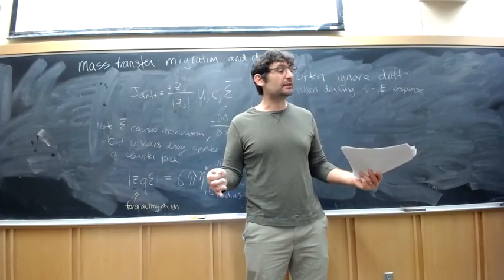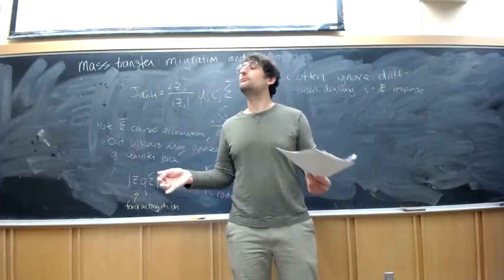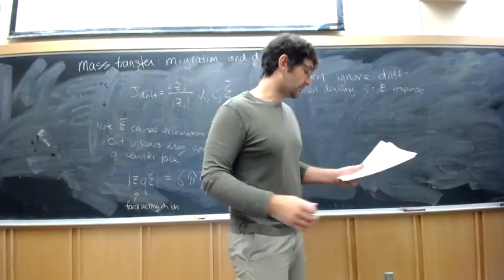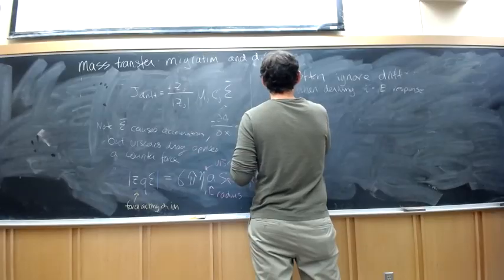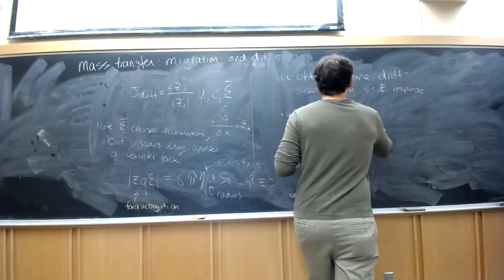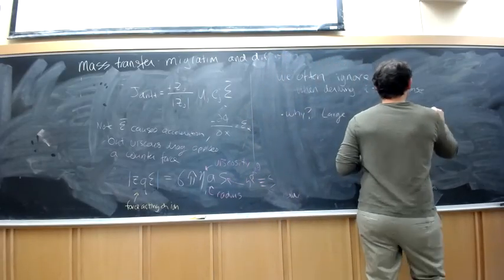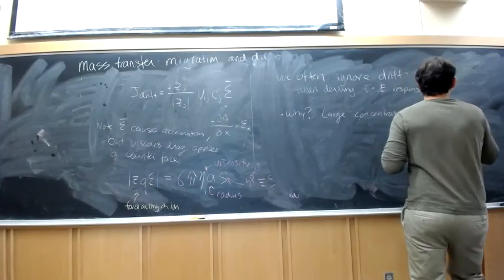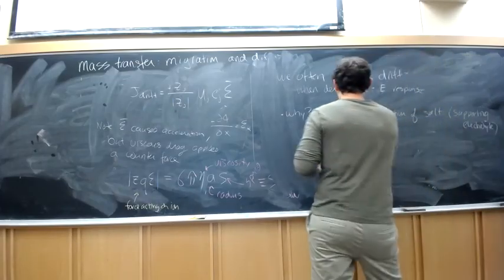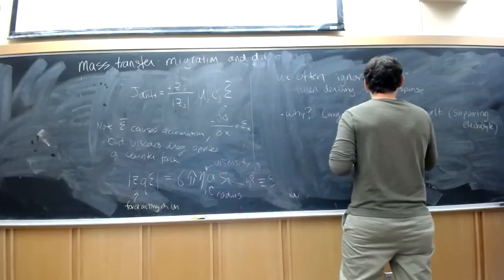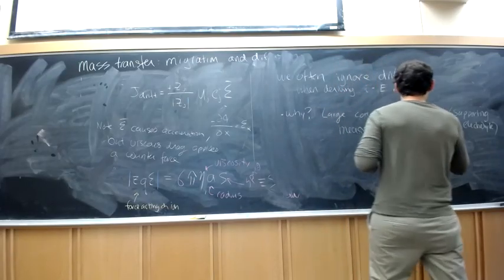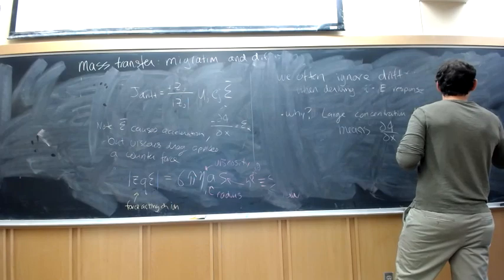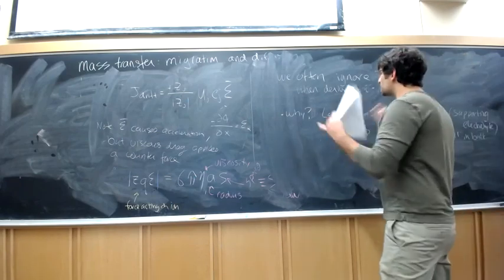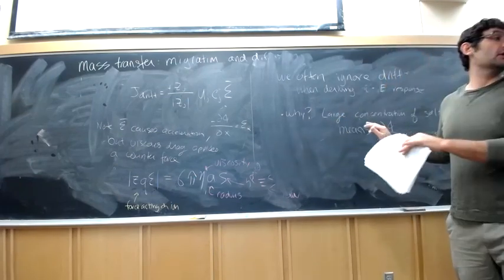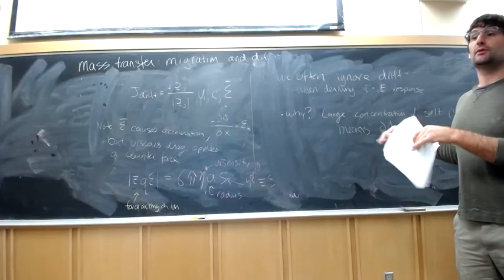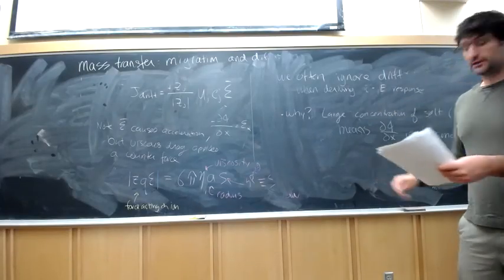Or you go to very low ionic strength electrolyte. Like you might not be doing electrochemistry in 1 molar salt, you might be doing it in 1 millimolar. Then migration terms become really important. So this is because a large concentration of salt, or we call it supporting electrolyte, means the dphi/dx is very small in the bulk. It only really changes a lot at the electrodes. And so this is a good assumption when currents are small and you have large concentrations. It's a bad assumption when currents are large or you have low concentrations.